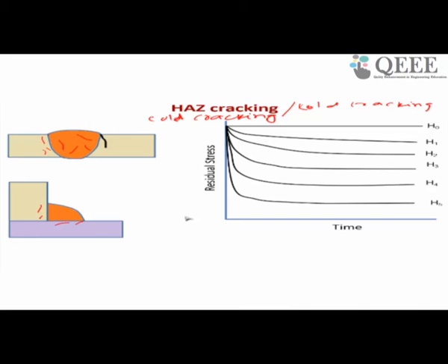During the melting step of the welding process, hydrogen will be entrapped inside the weld pool. Then if your solidification rate is very fast, during cooling this hydrogen has to come out, because hydrogen has very low solid solubility. As a result, you may get porosity. By chance, if it does not happen,